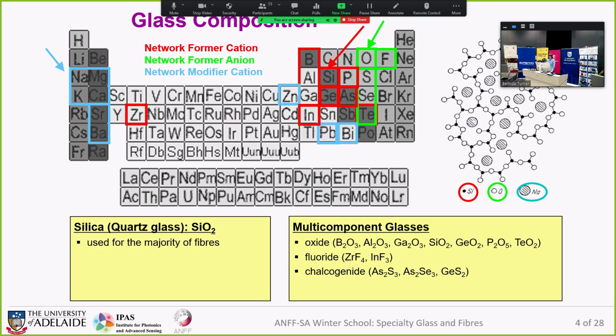Their anions are the chalcogens, sulfur, selenium, and tellurium, and the corresponding cations are germanium and arsenic. Of these many glasses, some have a softening temperature lower than 700 degrees Celsius, so they are called the so-called soft glasses, and typical examples are heavy metal oxide glasses like lead silicate, fluoride glasses, and chalcogenide glasses.